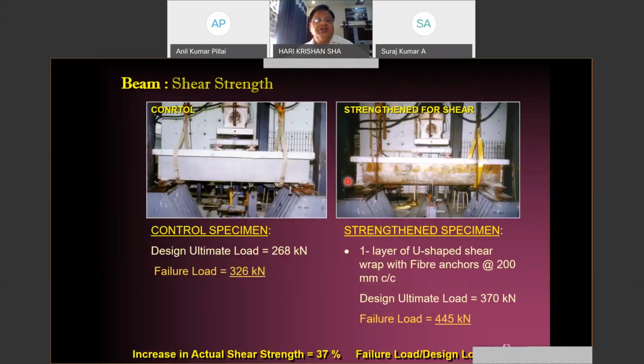You will find a control beam, which was tested. The design ultimate load was of the order of 268 kilonewton, whereas the beam failed at a load of 326 kilonewton. The same beam was then strengthened with one layer of U-shaped FRP shear wrap with fiber anchors at 200 mm center to center. The design ultimate load was increased to 370 kilonewton because now the FRP will also take some load.